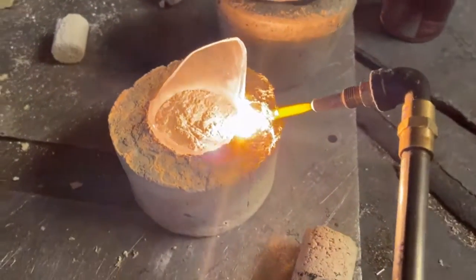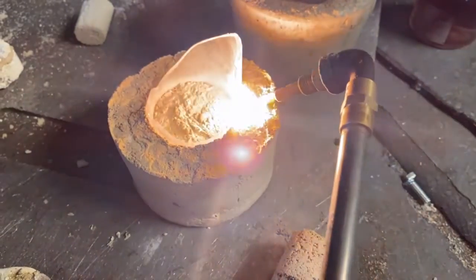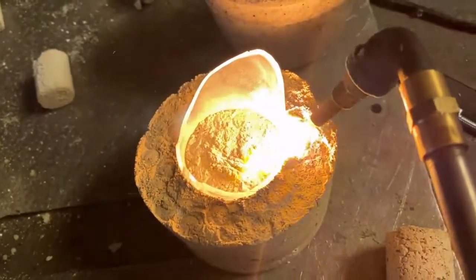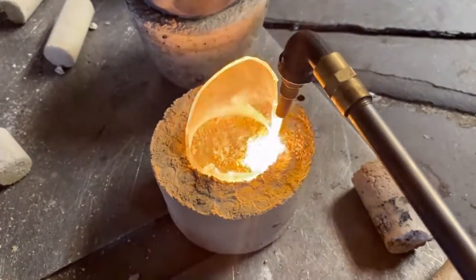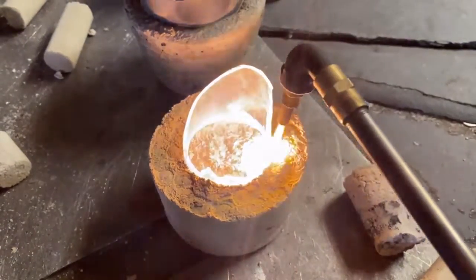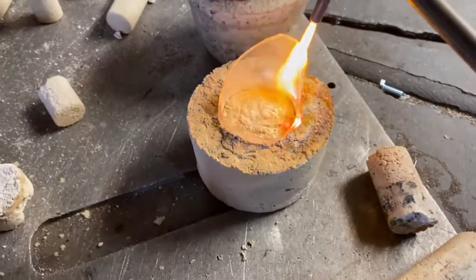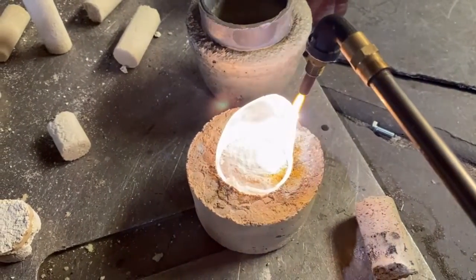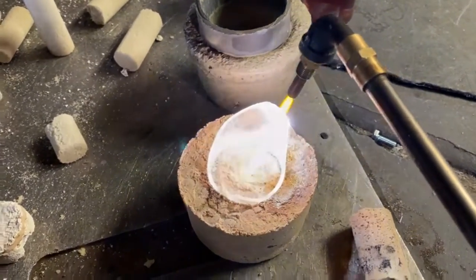It has some pretty amazing material — it's not the best thing in the world, don't get me wrong. I don't know that I would build a foundry out of this stuff just yet. It's right on the edge of being good enough. If it gets heated up really hot — like oxyhydrogen hot, super red hot — it does soften a bit. But as far as a repair compound or a crucible paint's concerned, I am very excited about this stuff.